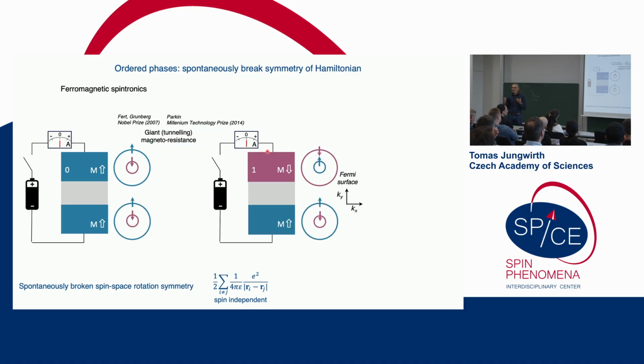So here came the extremely clever concept of spin valves, or giant or tunneling magnetoresistance devices, where you still have these two magnetic states, one pointing up, one pointing down, representing 0 and 1. But in the device, you have an additional ferromagnetic electrode, which is a reference electrode, where the spins are always pointing in the same direction. And now you can test in which of these two mutually spin-rotated states you are by sending an electrical current. And you can test it because the electrical current is carrying the spin information, because in ferromagnets the electrical current is spin polarized. So we have an electronic device here which is directly testing the broken spin rotation symmetry, or directly testing the broken symmetry in the spin space.